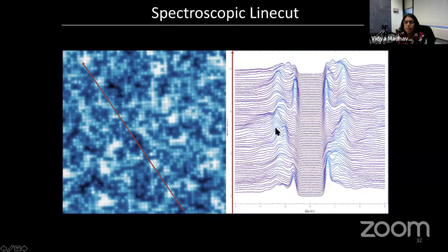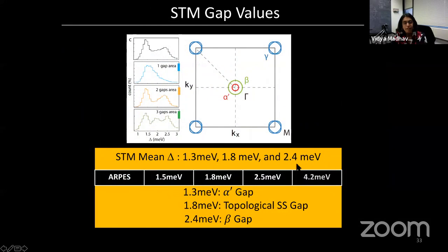However, as you march along, you can see many coherence peaks. In fact, if you look at this spectrum, you have 1, 2, 3 coherence peaks existing simultaneously. The reason is that you have many pockets that cross the Fermi energy, and in this particular compound each of these pockets has a different gap magnitude. That's what you see in STM. It's pretty easy for us to do a statistical analysis, pick up all of these gaps and look at their histogram. In fact, that's what we did.